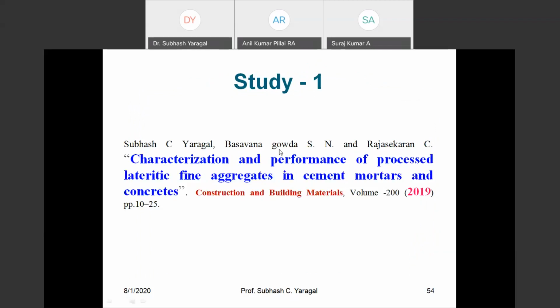Now the first work that I'm sharing here is the characterization and performance of processed lateritic fine aggregates in cement mortars and concretes. What we have done in this study is we have taken the lateritic sand, which is available in laterite deposits during the time of dressing of your laterite blocks. And we have come out with a systematic way of characterizing this lateritic fine aggregate. We have studied the performance of using lateritic fine aggregate in production of cement mortars and concretes.